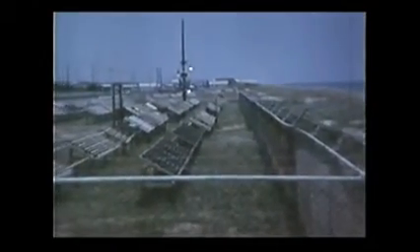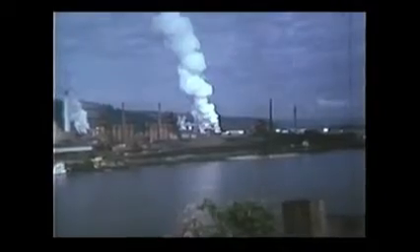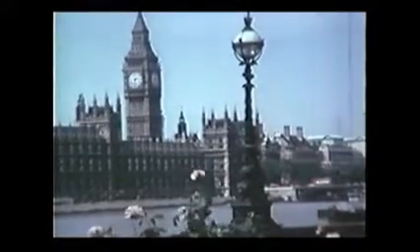How much lower depends on the location and the type of atmosphere. In Pittsburgh, Pennsylvania, after 2 years, the corrosion rate of steel was about 13 times higher than zinc. In London, England, 17 to 21 times. Ottawa, Canada, 19 times. In Melbourne, Australia, 37 times. And in Daytona Beach, Florida, the corrosion rate of steel was more than 160 times that of zinc.